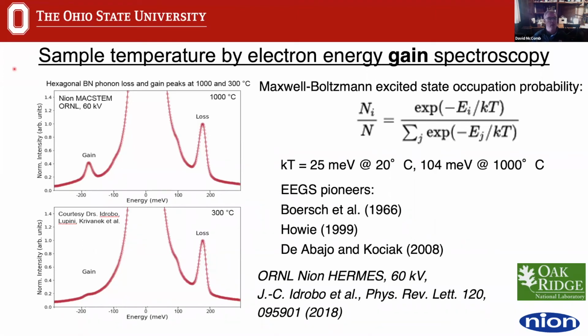Because what we see here, in the case of looking at hexagonal boron nitride, is that because we're able to get this energy resolution, we see this peak at about 150, 160 millielectron volts, and that's associated with exciting a phonon in the material. So this is a vibrational loss in boron nitride. But phonons, at finite temperature, are there within our material. So if we can excite a phonon with the electron, then we should also be able to transfer the energy of a phonon to the electron.